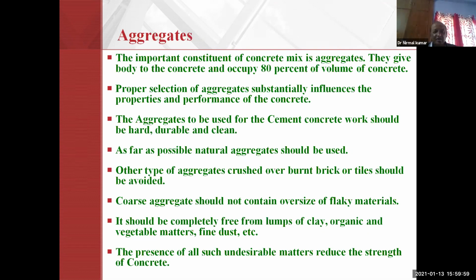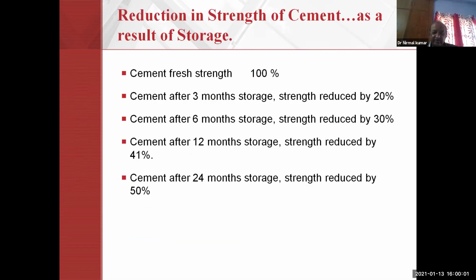If cement is fresh, then strength will be 100%. If it is 3 months old, then strength will be reduced by 20%. If it is more than 6 months storage, the strength will be reduced by 30%. If it is 1 year old, strength will be reduced by 41%. And if it is 2 years old, strength will be reduced by 50%.